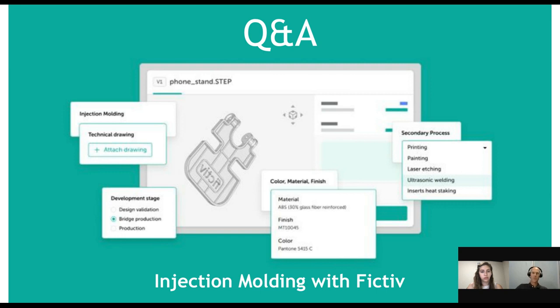It definitely is a contributing factor to that wear, because whether it's fiber or glass, it's injecting into that tool. It's running along that tool surface. So where it hits, you're creating a little bit more wear, especially at the point of the gate, where the plastic is actually being injected into that mold. That's where you typically start seeing the impact of fiber or filler in general on tool wear, which is usually why, in the industry, what you would get out of the same mold, same design, out of say an ABS material, you get 10,000 or 50,000, but you start adding glass, it knocks that tool life down, sometimes in half or more.